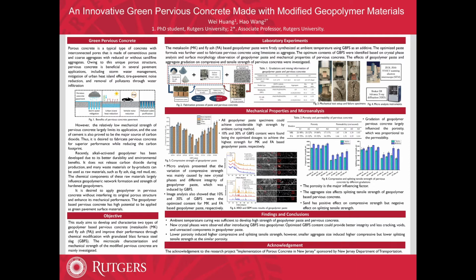The reason is that if we have more smaller particles, the interaction between the aggregates will be more complicated, and the friction during the compressive test will be higher. So the compressive strength is higher. However, the splitting tensile strength mainly comes from the bonding effect between the paste and the aggregate. So if you have more smaller particles, the thickness of the paste coated on the surface of the aggregate will be thinner, and the bonding effect will be weaker. As a consequence, the splitting tensile strength will be reduced.